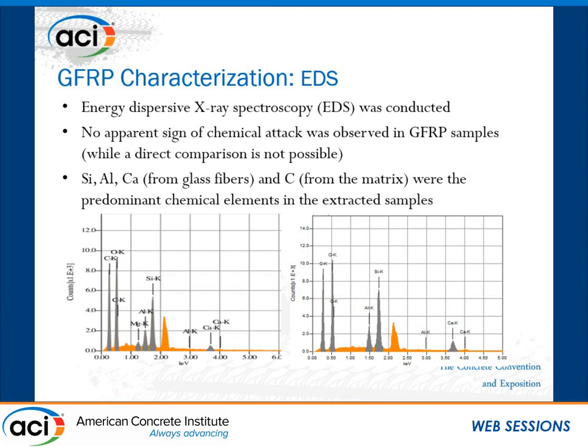I completely agree with you. As I mentioned, the perfect situation would be having the exact samples, and we had that situation for a different bridge in Texas. We compared the shear test with the same shear test data which had been performed 15 years ago, and those are the perfect evidence. But still, we cannot perform these tests on several repetitions of samples, because we cannot core more than a certain amount of samples.